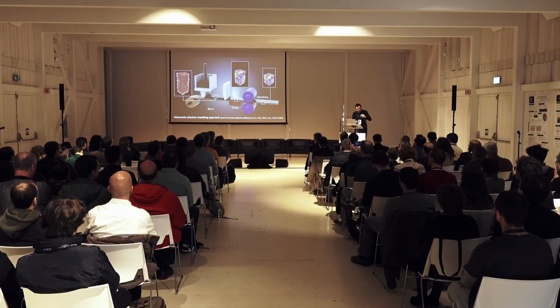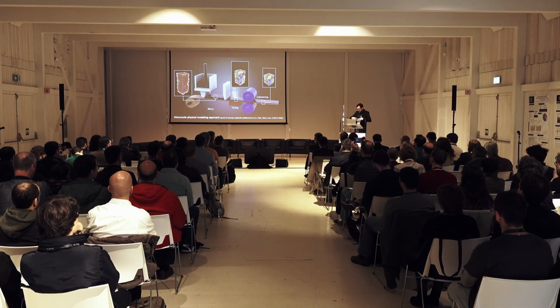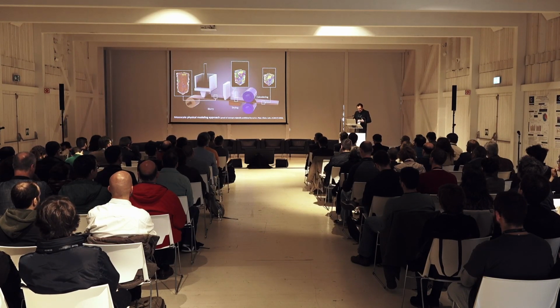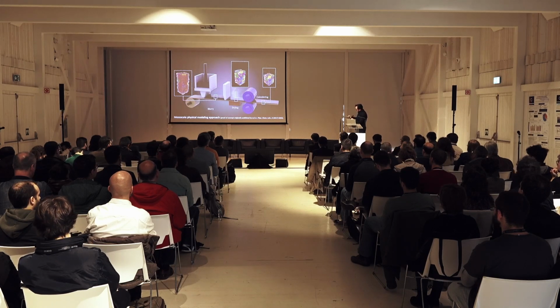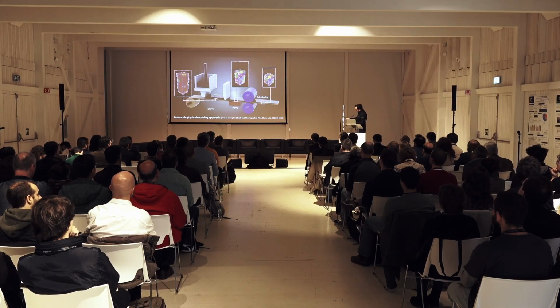Basically, here we are using a collection of MD, molecular dynamics-like tools, which are actually not resolving the interaction between molecules. Here, what we resolve is the interaction between particles at the mesoscale. So these particles here, they have micrometer size, okay? So the models actually simulate the slurry, which is actually an ink, where you have a suspension of the active material, the carbon, the binder, which are the essential components, the essential materials you have in the electrode. These particles and these materials are in suspension in a solvent.